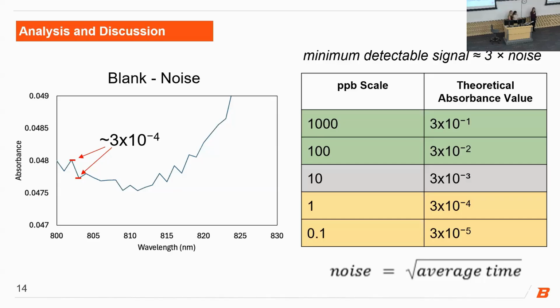We looked at the data from our blank, and we determined that the random noise is about 3 × 10⁻⁴ absorption units. And then we used the instrument response from our highest concentration of our sample, and we generated a table of theoretical values of instrument responses for lower concentrations. We compared this to the random noise to determine the lowest concentration we should theoretically be able to detect with this noise level. A good signal is at least 3 times the noise. We determined that we should theoretically be able to detect 10 parts per billion with this level of noise because our theoretical signal is still 10 times our noise level.